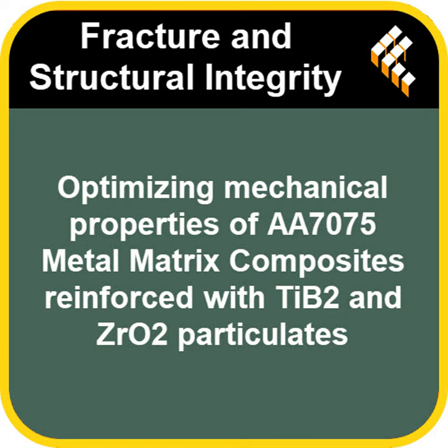The key finding, perhaps unsurprisingly by now, was that the AA7075 composite with 5% TiB2 and 4% ZrO2 showed the best wear resistance. It had the lowest wear rate under the test conditions. Champion again. It seems so. The mechanism here is quite neat. Those hard ceramic particles, the TiB2 and ZrO2, they don't just act as obstacles, they can also act as sort of solid lubricants during sliding contact.